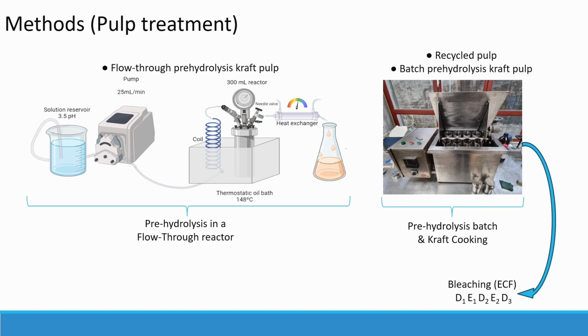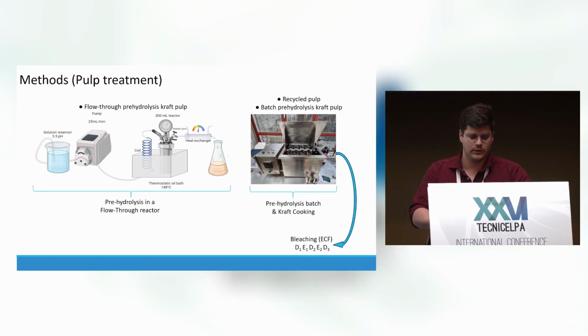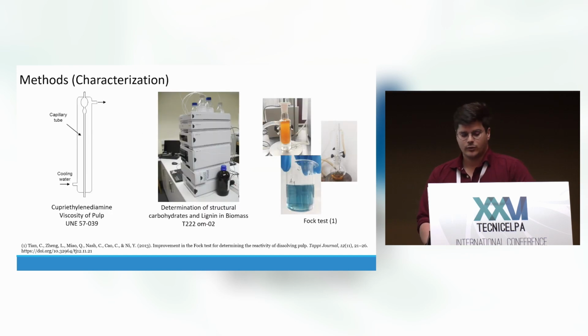In the other part of the project, we worked with recycled pulp. It's a pulp at the end of its life of utility. It has specific characteristics that are more difficult to work with. For both pulps, we did the KRAFT cooking in the batch system, so the only difference is the PREHYDROLYSIS reactor. Regarding characterization, as I mentioned before, it's important to follow the viscosity of the pulps. We also studied the composition of the pulps, and we did the FOCK test. FOCK test is a mini scale of the viscose process.